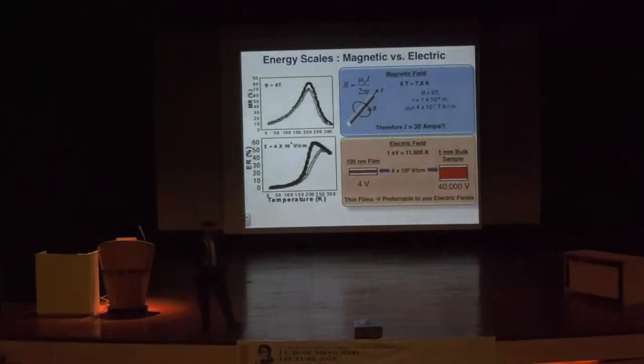Okay. So here's an example for those of you who work on manganites, colossal magnetoresistive materials. That is the MR. This is for lanthanum calcium manganese oxide. And it basically shows you that you have a huge 70, 80, 90% change in the resistance of the material with a magnetic field of about 6 Tesla. Okay. At the bottom, you have the parallel universe of colossal electroresistance, where the resistance changes by about 60% with a field of about 400 kilovolts per centimeter.